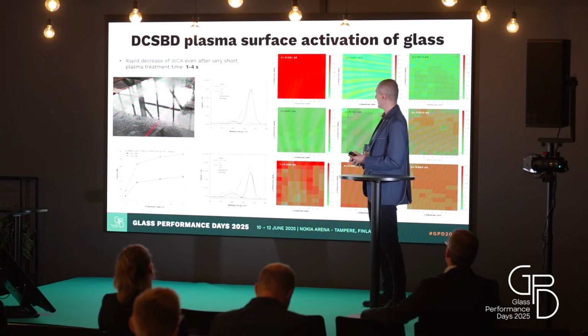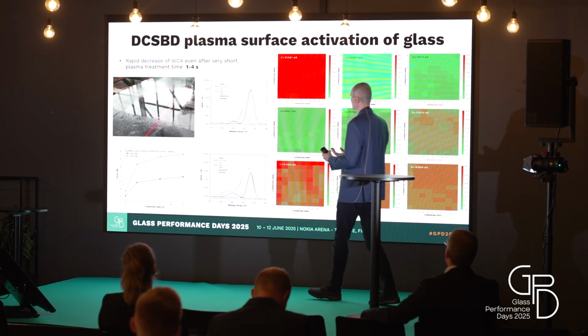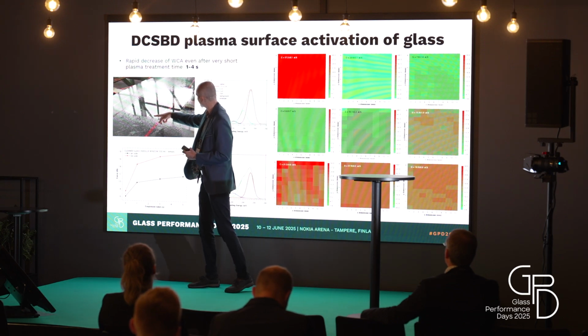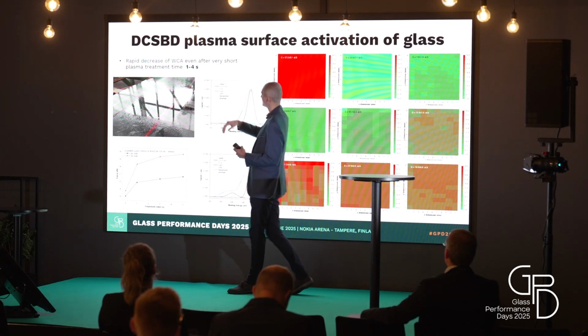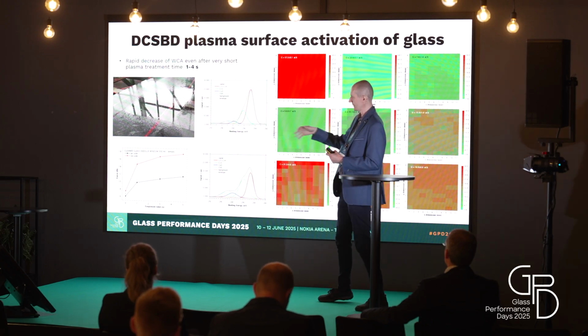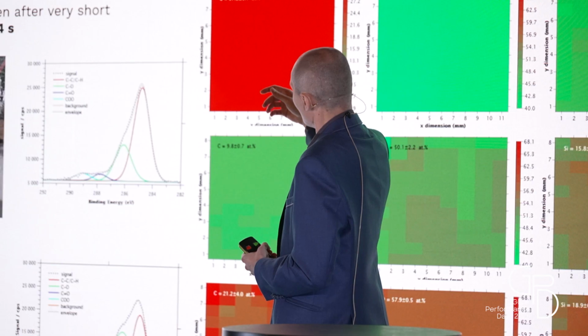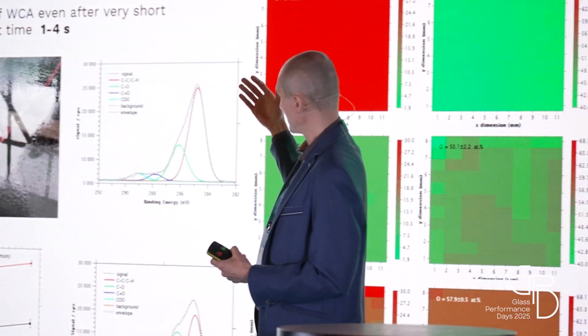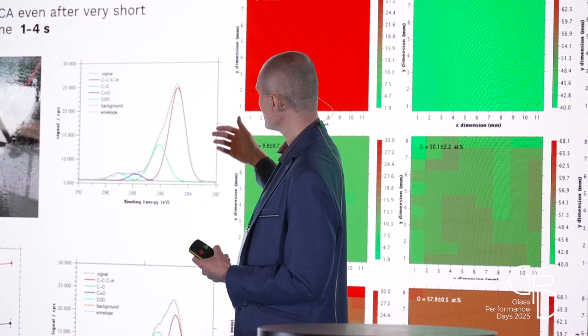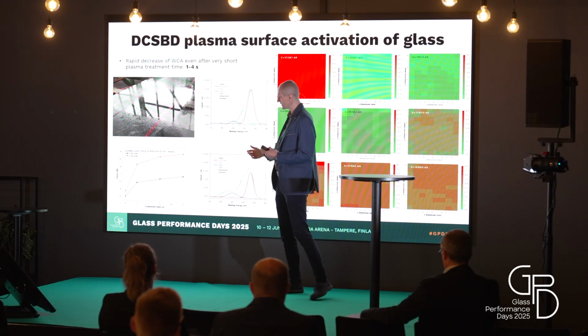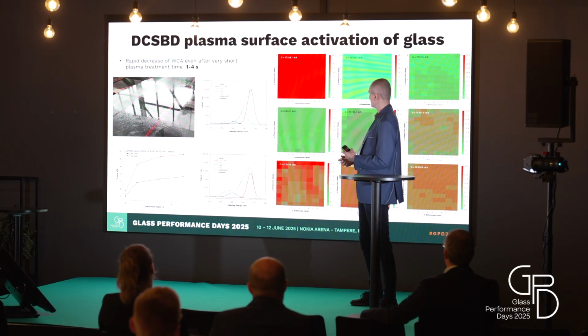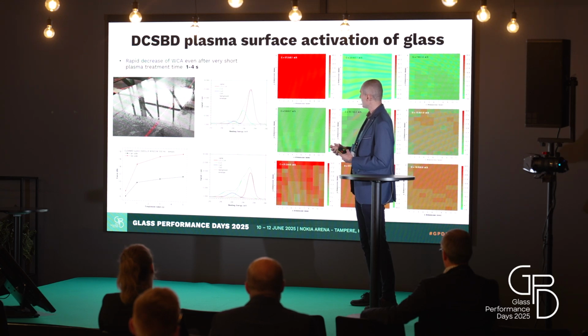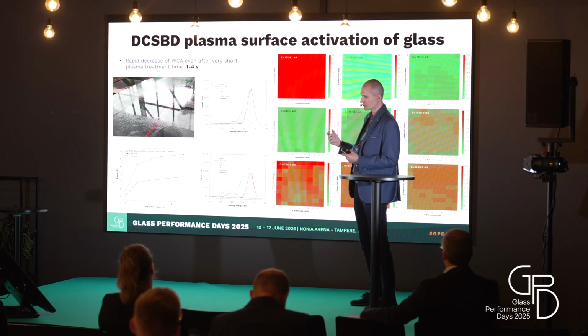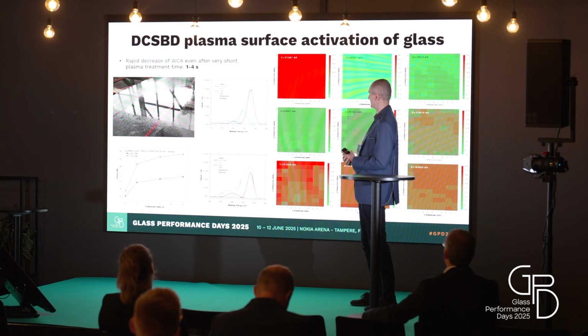The effect of plasma on the glass is, okay, we can turn it, we can clean it, and we can create a nicely uniform, very hydrophilic layer on the glass surface. We clean it, we remove, for example, carbon concentration, we initiate some oxygen-related bonds on the surface, which in turn improve that hydrophilicity. As a result, we also improve the adhesion force on the glass surface, and we do it on both sides, on the air side and also the tin side.